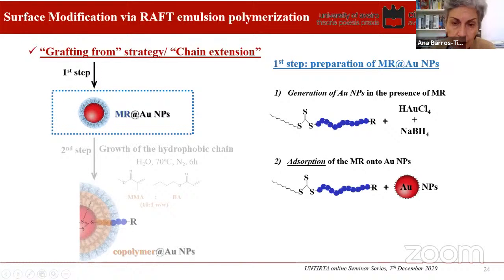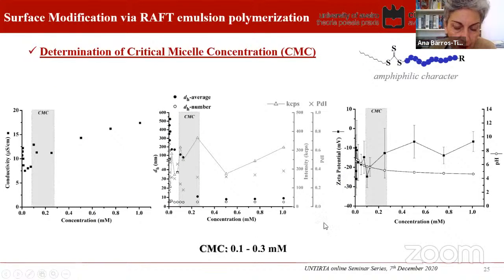In the first step, we have the preparation of these macro RAFT chains adsorbed at the gold nanoparticles. So it involves the generation of gold nanoparticles in the presence of the macro RAFT agent, and the other one involves the adsorption of the macro RAFT agent on pre-prepared gold nanoparticles. This is all okay, but we have to bear in mind that the macro RAFT itself has amphiphilic characteristics. So working above or below the critical micelle concentration is a major issue. The problem is how to determine the critical micelle concentration of polymeric material that is not really charged.